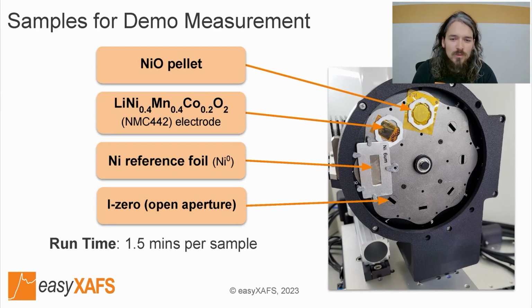For the demonstration, we'll be measuring at the nickel K-edge. So we'll measure 3 samples: a reference nickel metal foil, an NMC 442 electrode sealed in Kapton, and a pellet made from nickel oxide mixed with binder. So we'll measure 1.5 minutes per sample, and then do the same thing through an empty sample wheel spot for the I0, and then we'll go through those results together.